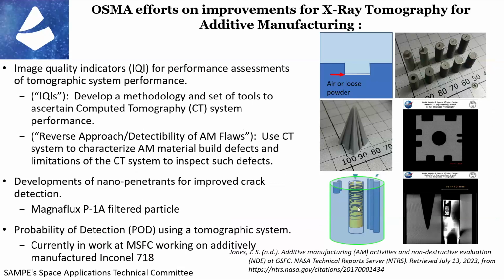So we started developing these image quality indicators specifically designed for CT. So you can kind of see all the designs here, and all of this has been, for the most part, made public, especially these ones I have on the screen here. But started printing these so that we could try to qualify our CT systems using a known geometry. And then what we found was a lot of the printers couldn't print below what the resolution of the system was, so we started adding extra line pair gauges inside the IQIs to do that. But you'll notice none of the edges line up. And this is a pyramid that should go to a point. So you effectively have your three-dimensional version of what the normal X-ray line pair gauge would be, which is pretty cool. And I'm going to talk a little bit more about this in just a minute.